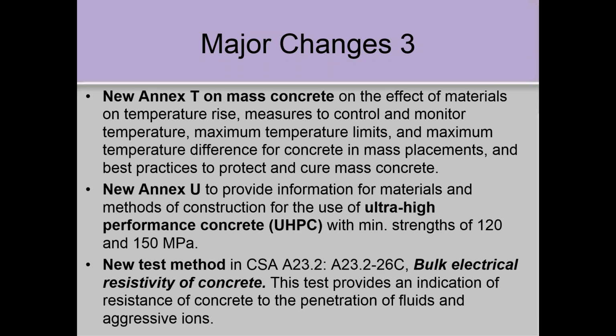We're talking about ultra high performance. We have two classes, minimum strengths of 120 and 150 megapascals. But some of these concretes are getting 250, 300 in some cases, but we've set these limits at 120 and 150. And we have one new test method, A23.2-26C, bulk electrical resistivity of concrete. And again, this is similar to the 23C, the rapid chloride permeability test, but it just measures electrical resistance, and instead of spending the whole day measuring the Coulomb values, you can do this test in about 1 minute, and essentially it gives you the same information.